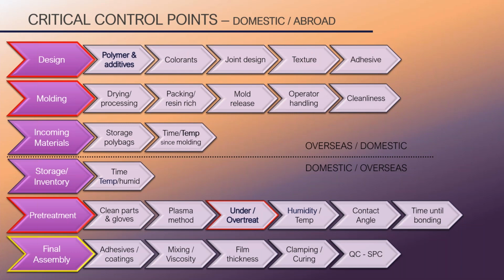How well is the operator handling the parts at the machine? Are they wearing gloves? And what about the cleanliness of the conveyor? If the machine operator and the conveyors are dirty with grease, then you're going to have cross-contamination. Then let's look at incoming materials. After injection molding, how have the materials been packed? Are they in poly bags? Well, if they're in poly bags, that's probably one of the worst packaging methods there is, because the poly bags often contain low molecular weight species that migrate to the surface. So if in fact that's how they're packed, then it's very common for some parts that have been in more intimate contact with the packaging to be contaminated.